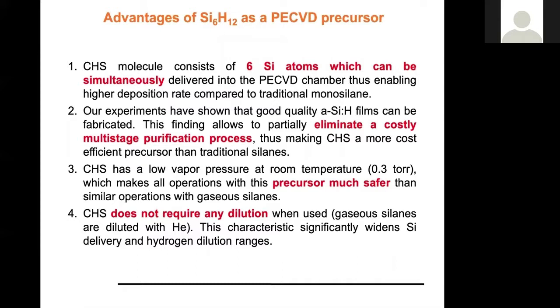Thinking now about making silicon thin films using PE-CVD, which is becoming the preferred method to make silicon-rich anode materials, here are some advantages of CHS. Compared to monosilane, it has in a single molecule 6 times as many silicon atoms. This is one reason behind the faster deposition rate.